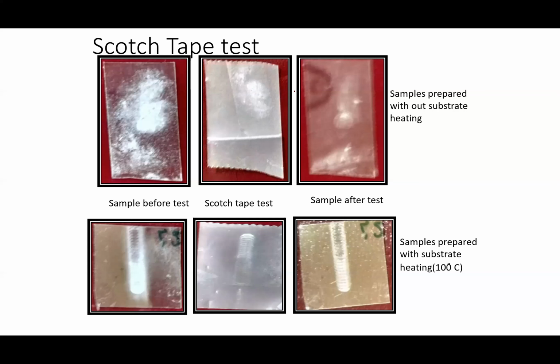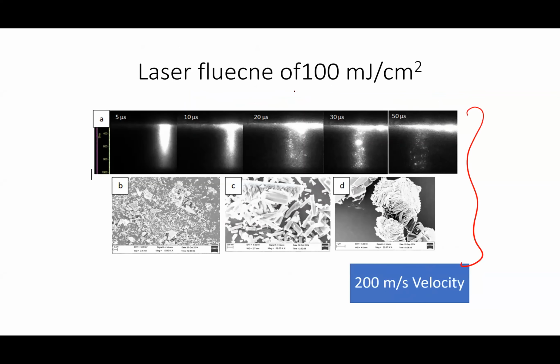So in order to take care of the adhesion, we are just keeping a plate heating, so that we prepare the surface so that the particle gets adhered to it. This is a kind of Scotch tape test to confirm how the adhesion looks. Okay, so we got a better adhesion, and the most important thing is it is something like throwing a particle on a wall at a very high velocity.